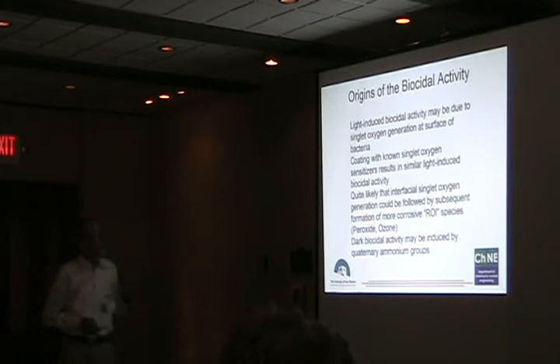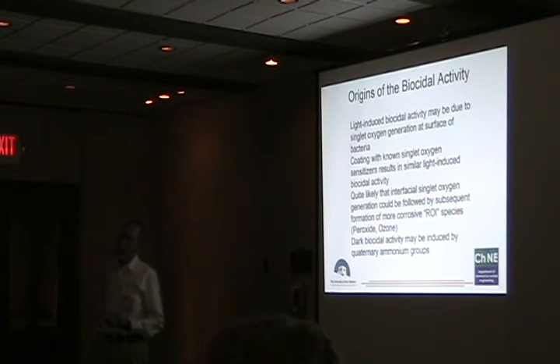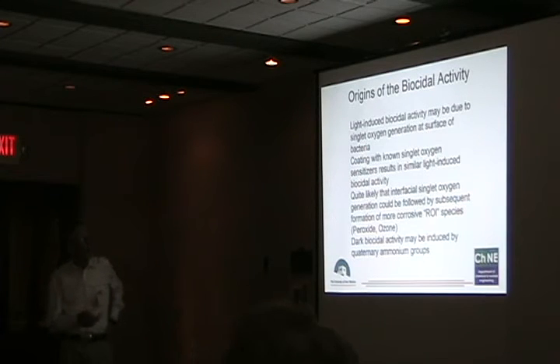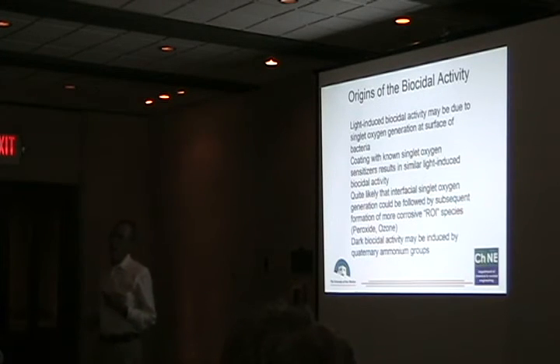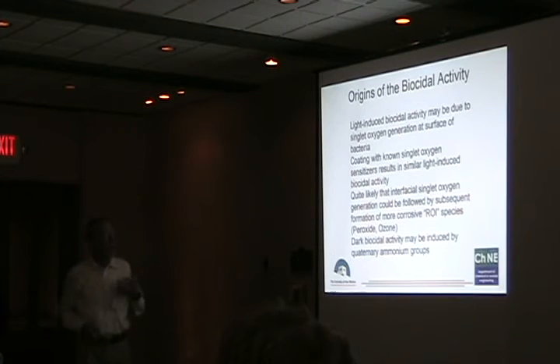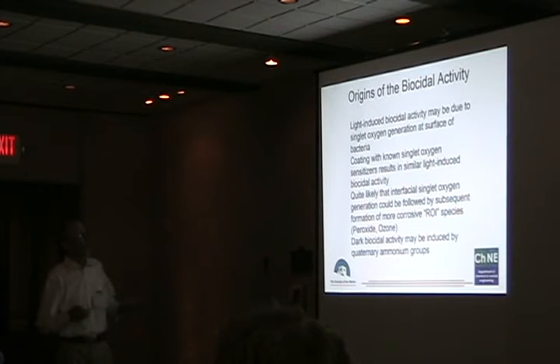We think that it's an interfacial singlet oxygen generation, and there's been a lot of speculation in the literature, and actually some fairly good cases made by workers, for example, at Scripps in San Diego, that you generate singlet oxygen in an interfacial environment where you have water, but not very much of it, and not bulk water, so that you can get nucleophilic attack of the water on the singlet oxygen and formation of more corrosive reactive oxygen species.